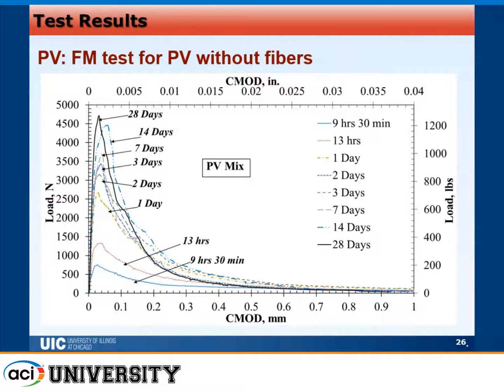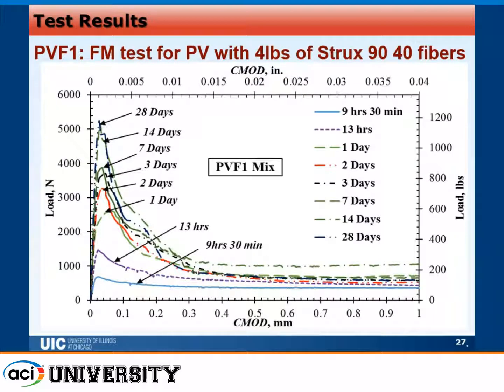Another observation is, as we increase the age from 9 hours up to 28 days, the maximum peak load will increase. But at some point around here, after we pass the 3 days, the gain in the peak load strength is less significant than the initial gain from 9 hours to 3 days. Similar observation was seen with fibers. However, the fracture toughness obtained with fibers was much higher.